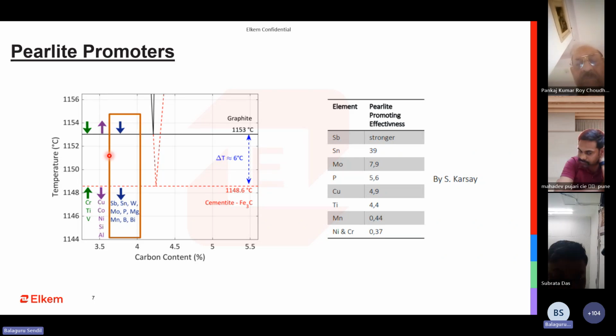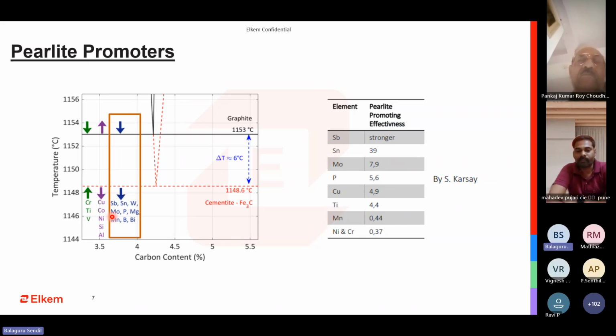There are some elements which can actually promote this irrespective of the cooling conditions. If you want to knock out a bit slow, if you have certain elements, you can still achieve pearlite. Or the other way around, if you want to knock out a bit early and still want to have ferrite, then you can achieve this.